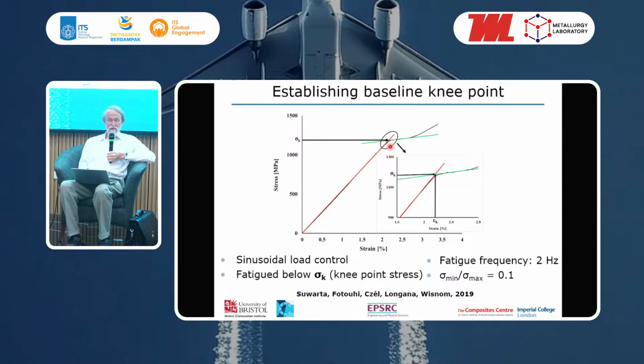So the first thing to do here is to establish the behavior statically. So this was loaded statically, and we got a knee point strain and a plateau on the stress strain curve, and this point here, where that plateau starts, is referred to as the knee point stress. The knee point stress was established by fitting these lines here, and then the specimens were loaded in fatigue under load control at a frequency of 2 Hertz, and they were fatigued below this level. So they were fatigued at multiple cycles at less than this knee point strain, and at an R ratio of 0.1, the ratio of minimum to maximum stress.